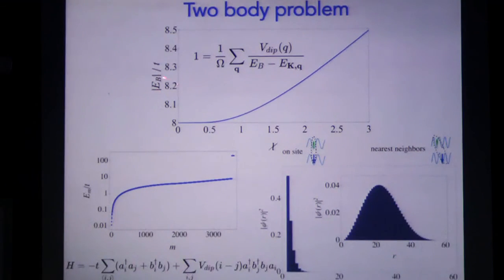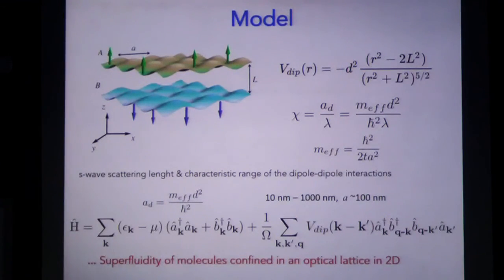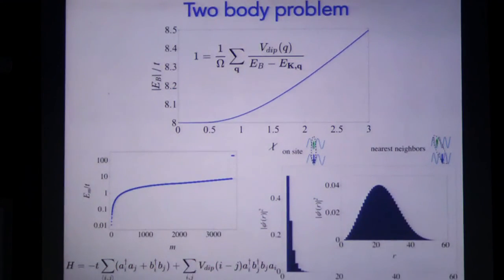So you can see that here I'm plotting the absolute value of the binding energy, this E sub B, and what you can see here, what is chi? So remember that chi is proportional to D, and D is the effective interaction that can be varied as a function of an external field. So the problem to be solved then depends, of course, on the value of chi. So this is just the two-body problem.